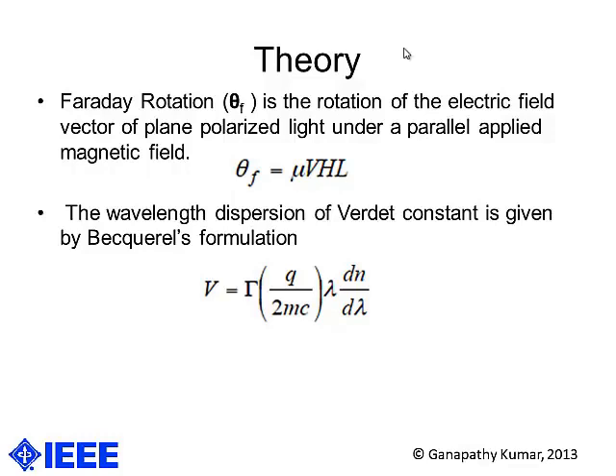And the wavelength dispersion of the Verdet constant is given by Henri Becquerel's formulation, where V equals gamma times e over 2mc times lambda times dn over d lambda. Gamma is a factor called the magneto-optic anomaly, which compensates for theoretical and practical differences in measurements. And dn over d lambda is the chromatic dispersion factor for the sensor that we're developing.